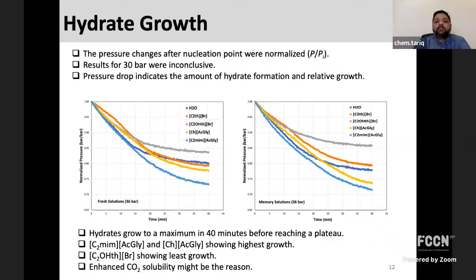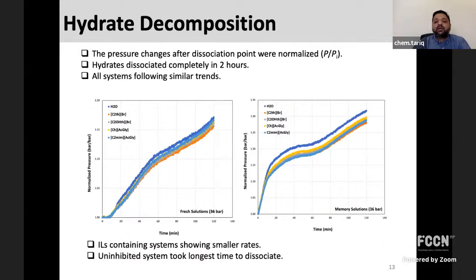Then we normalize the pressure from the nucleation point onwards, and we saw that at 30 bar the results were not conclusive. So that's why we presented the results at 36 bar. What we see here is that two of the ionic liquids, which are amino acid based ionic liquids, are showing higher growth compared to the thiouronium one. It can be because many amino acid based ionic liquids are known to solubilize CO2 very well. And in the case of hydrate decomposition, we saw that all the ionic liquid containing solutions decompose much more easily compared to the uninhibited system.